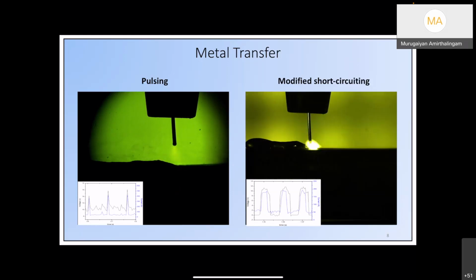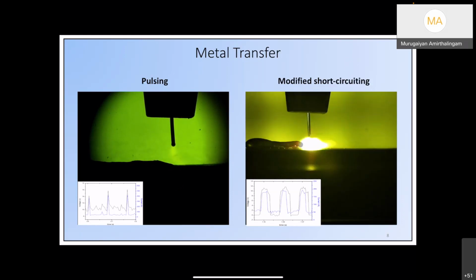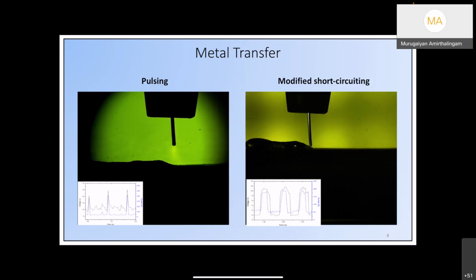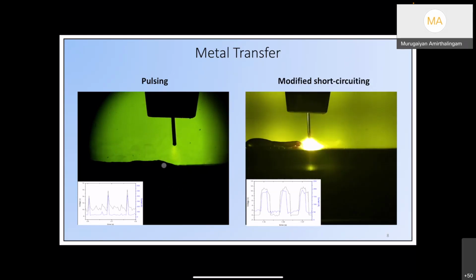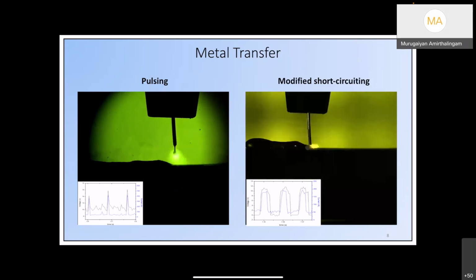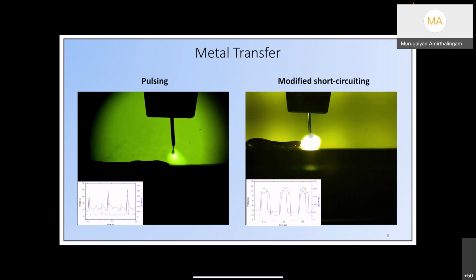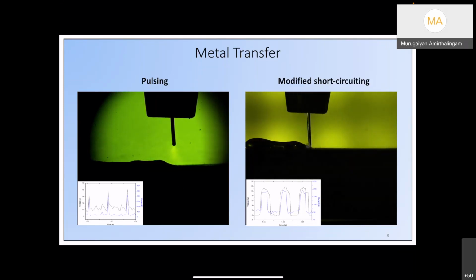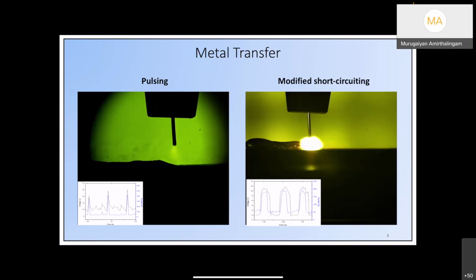So what does it indicate? When this transfer takes place, the top and bottom surface temperature of the molten pool would be more or less the same, or just a small difference in the temperatures. You can already correlate the graph I showed you, isn't it? In one case, we have a steeper temperature gradient. In another case, we have a shallow temperature gradient. And moreover, this wire is dipping, and this is a cold wire, isn't it? So during this process, it can also extract some heat from the molten pool to minimize the temperature gradient. So what happens when we do this trick?